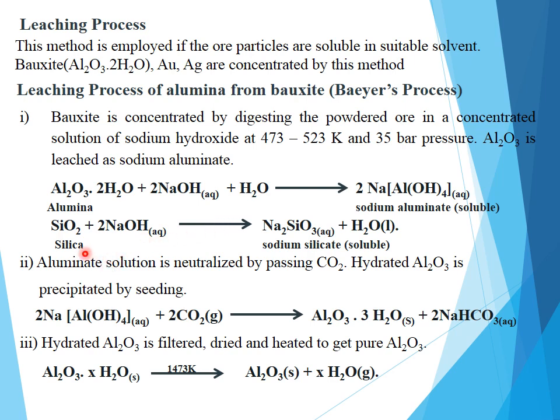In the next step, this aluminate solution, as it is basic in nature, will be neutralized by passing carbon dioxide gas, and to convert it into precipitate, we add a small amount of hydrated alumina, which causes precipitation of this alumina, and that we call the seeding process. The sodium silicate solution will remain as it is soluble, whereas aluminate solution will come out in the form of precipitate, which is called hydrated alumina. Upon passage of CO2 gas, it will be neutralized, and upon addition of hydrated alumina, the precipitation process increases.